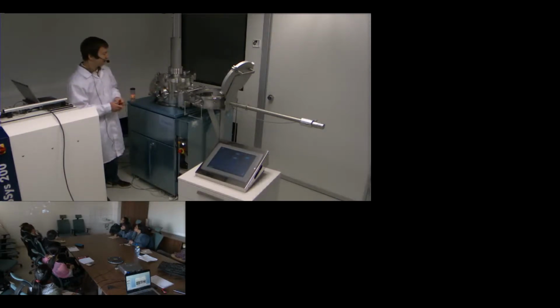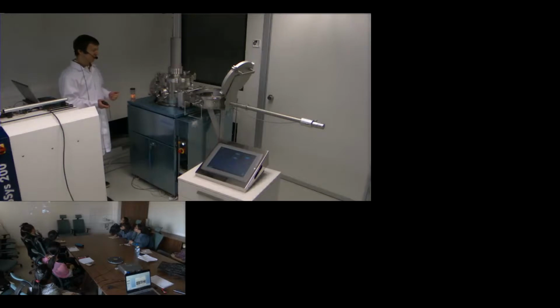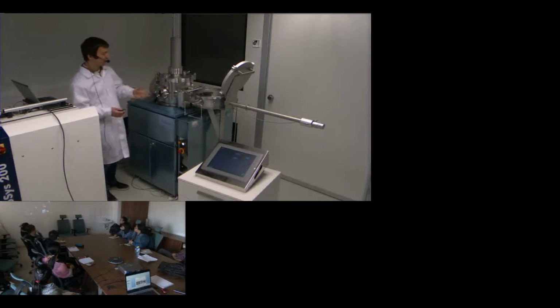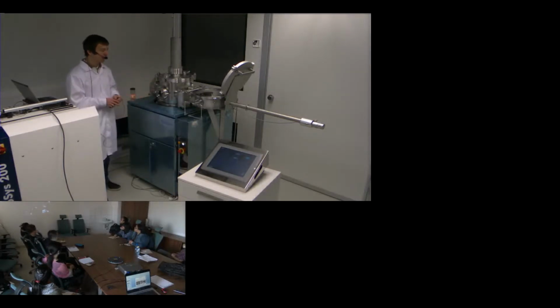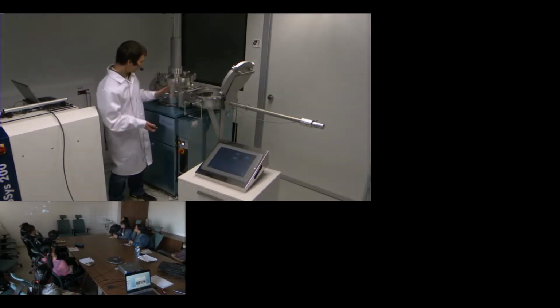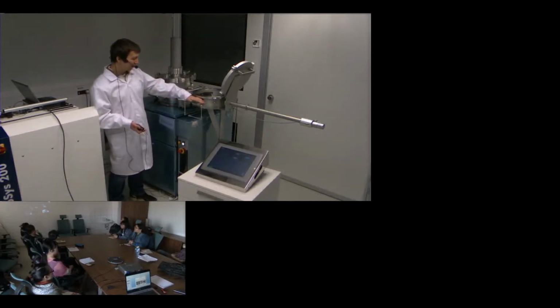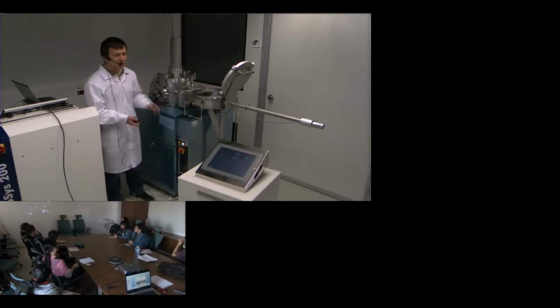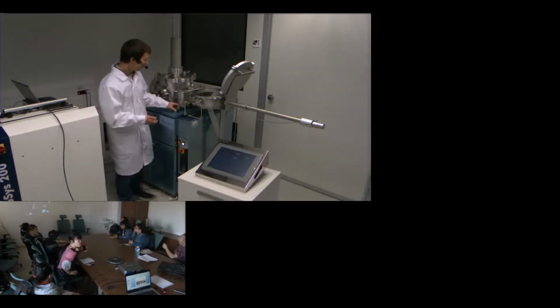This is the atomic layer deposition apparatus. In general it's like a stainless steel box where we have some vacuum. We have vacuum pumps which evacuate the whole space, so we have even more idealized conditions for materials preparation. Then we have several chambers. This is the load lock, a place where we put our sample.